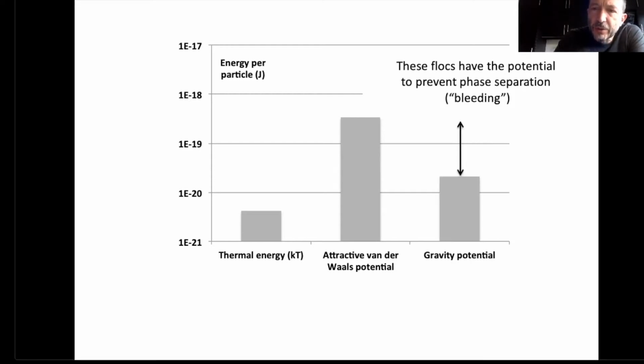And last but not least, gravity potential is systematically lower in magnitude compared to the attractive van der Waals potential. It means that the flocs that are being formed are stronger than the gravity-induced potential, and it means that these flocs have the potential to prevent phase separation or bleeding and make the system stable.